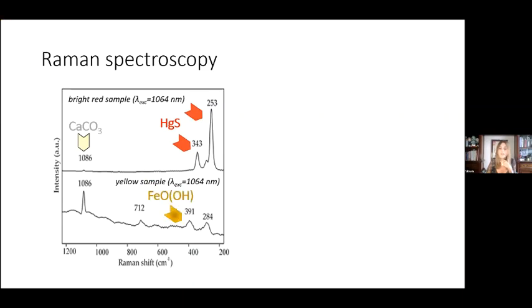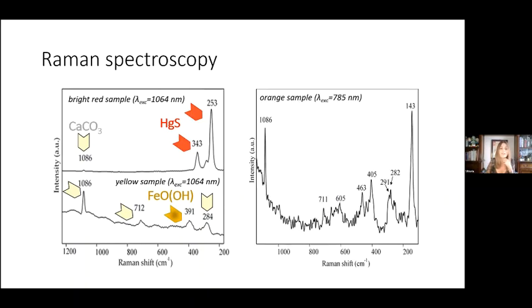In fact, the band at 391 cm⁻¹ is certainly ascribable to goethite, whereas the bands at 1086, 712, and 284 cm⁻¹ are due to calcite. Then the spectrum obtained on the orange sample appears as the overlapping of the bands of red ochre, yellow lead oxide known as massicot, and calcite, and also present was some yellow ochre identified by a shoulder at 391